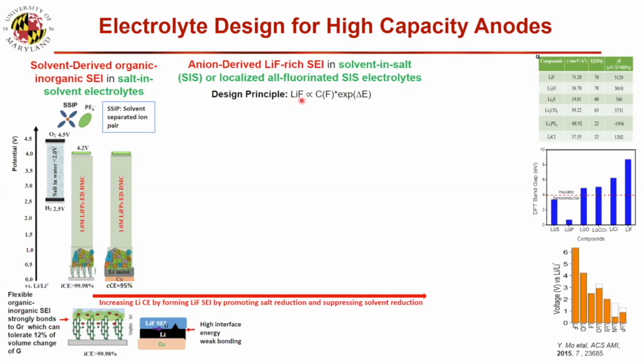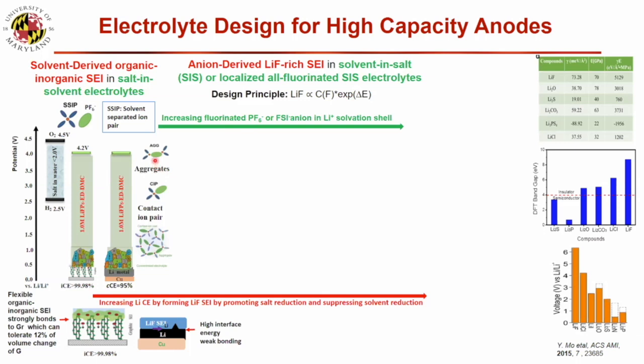If we want to largely reduce the anion, we should bring more anion concentration. Also, we want the solvent to have a lower reduction potential, whereas the anion has a high reduction potential, so they have a very large reduction potential gap. First we talk about how we can increase fluorinated anion concentration. One way is we put a lot of salt, either PF6 or FSI.